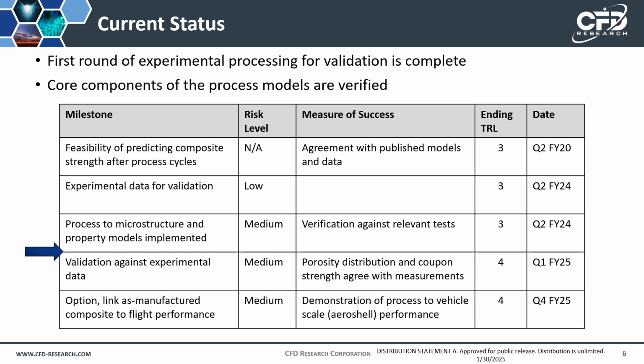We have verified the key components of the model against benchmark tests. A first round of composite processing for state-of-the-art materials has been completed, and our partners have performed thorough characterization including CT scans before and after key process steps, as well as mechanical testing. The model has been shown to predict the distribution of porosity well, with stresses and strains also agreeing with the location of cracks and fiber bundle separation seen in the experimental samples.